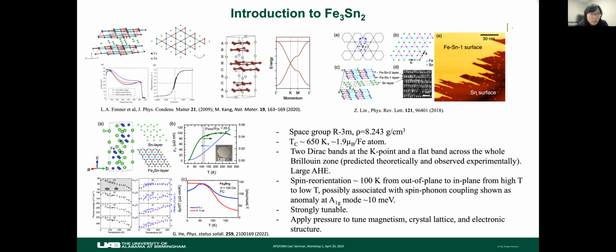The crystal structure, the unit cell, is trigonal, R3m. Previous calculations, and also later observed experimentally, show a very interesting band structure. It's shown here. You can see my mouse. The interesting thing about this compound is there are two Dirac bands at the K point, and also a very flat band across the whole Brillouin zone. And that's pretty unusual. That's coming from this unique Kagome